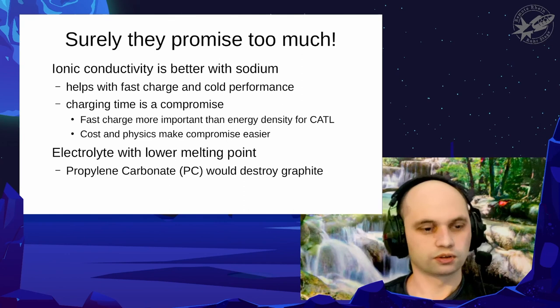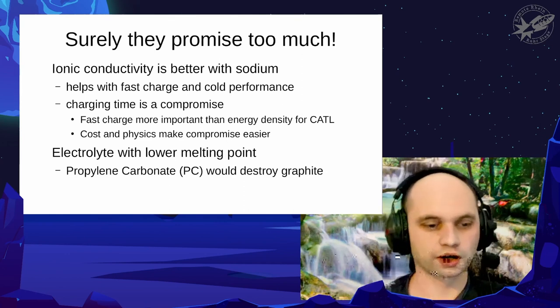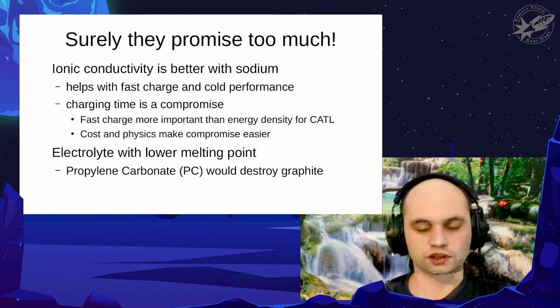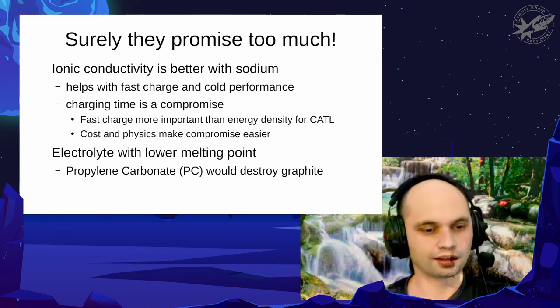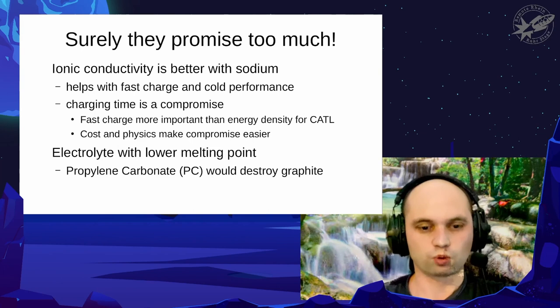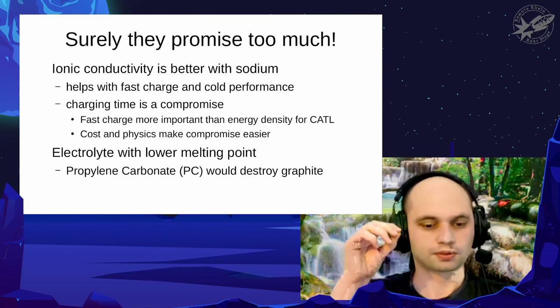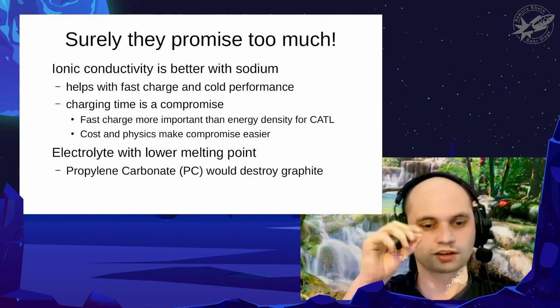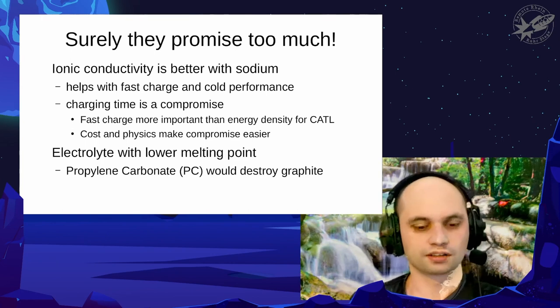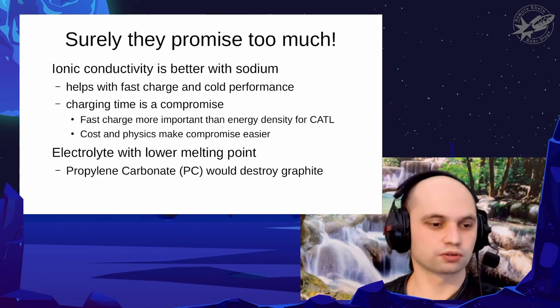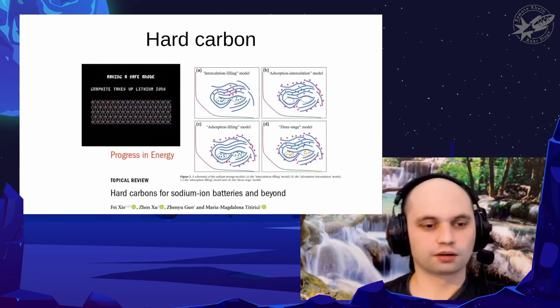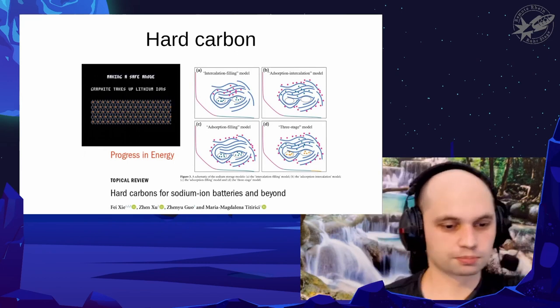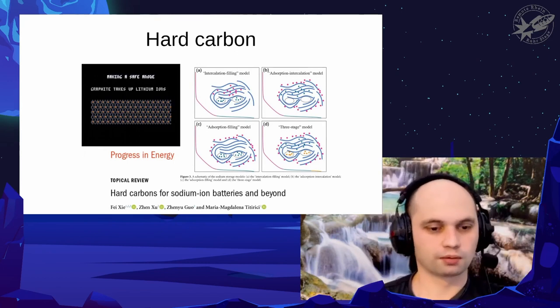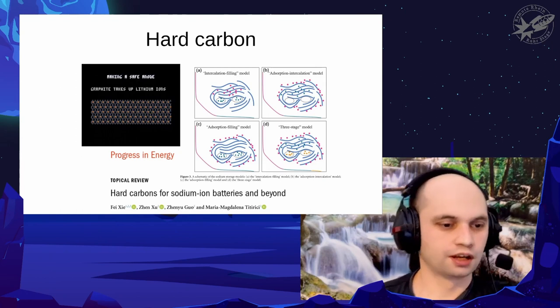Also, the electrolyte that you can use is propylene carbonate, and normally you cannot use a lot of that because it would destroy graphite, and you'd use graphite in the lithium-ion battery as the anode. With sodium, graphite doesn't work. You use graphite because you can put the lithium ions in the layers between the layers of the graphite, but sodium is bigger and it's too big for graphite, and so you cannot use it. And so you can use the propylene carbonate and just benefit from that because it has a much lower melting point and you can use it at freezing temperatures.